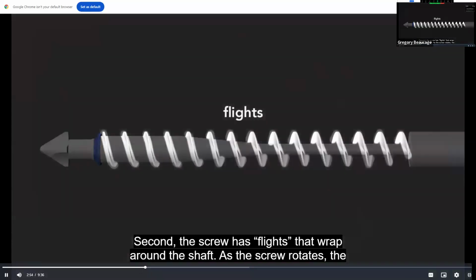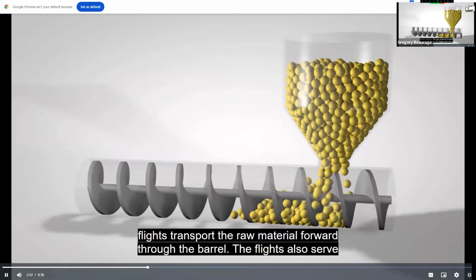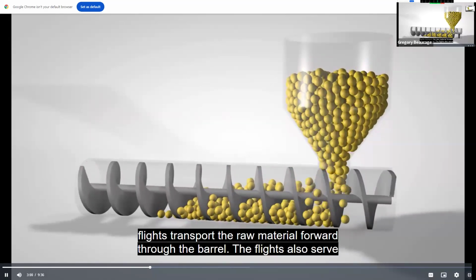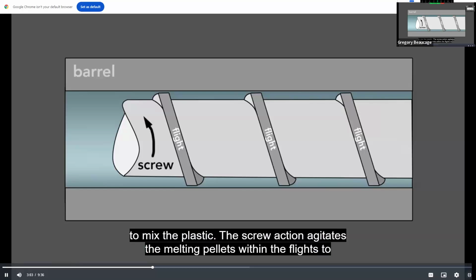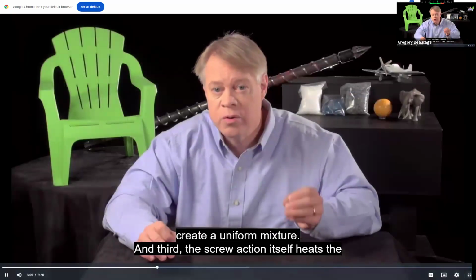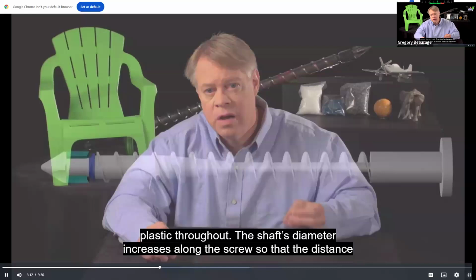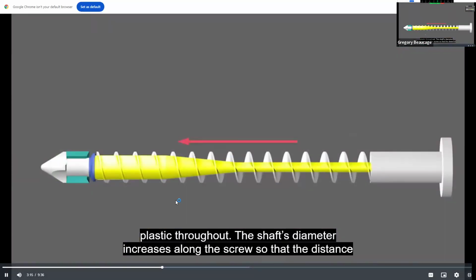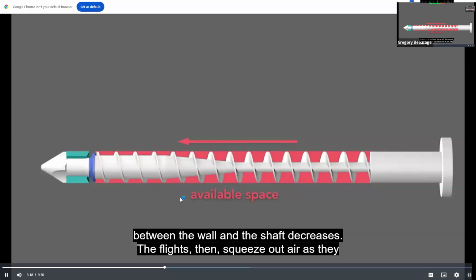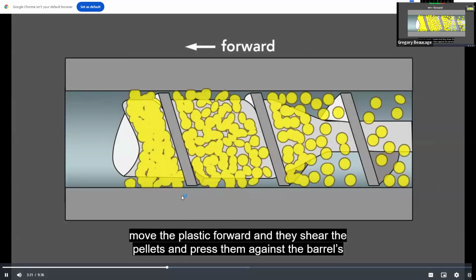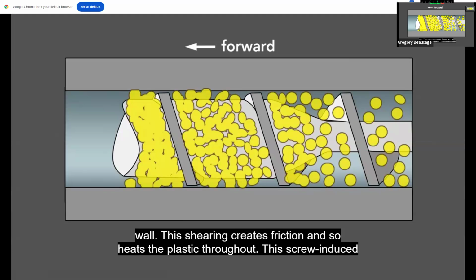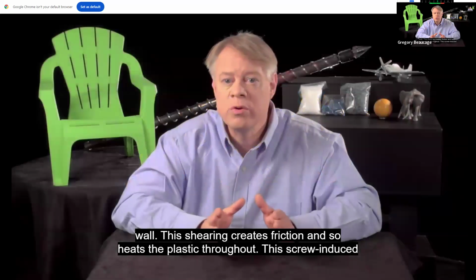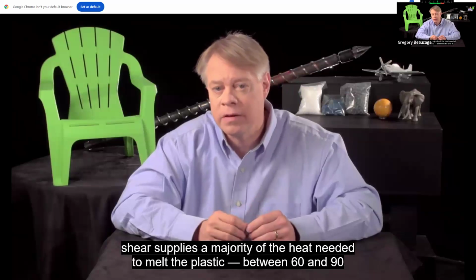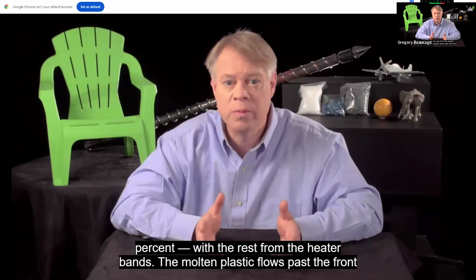The screw has flights that wrap around the shaft. As the screw rotates, the flights transport the raw material forward through the barrel. The flights also serve to mix the plastic. The screw action agitates the melting pellets within the flights to create a uniform mixture. And third, the screw action itself heats the plastic throughout. The shaft's diameter increases along the screw so that the distance between the wall and the shaft decreases. The flights then squeeze out air as they move the plastic forward, and they shear the pellets and press them against the barrel's wall. This shearing creates friction and so heats the plastic throughout. This screw-induced shear supplies a majority of the heat needed to melt the plastic, between 60 and 90%, with the rest from the heater bands.